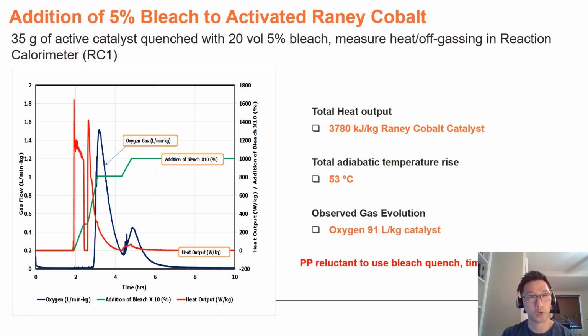So in order to quantitatively assess the hazards of using bleach to quench Raney cobalt, what we did is we took 35 grams of Raney cobalt from our supplier. We put it into a Parr vessel and hydrogenated with about 4 or 5 bar of hydrogen to mimic reaction conditions. We then took that activated catalyst and we measured the heat and off-gassing when quenching with 20 volumes of 5% bleach in what's called our RC1, or reaction calorimeter.